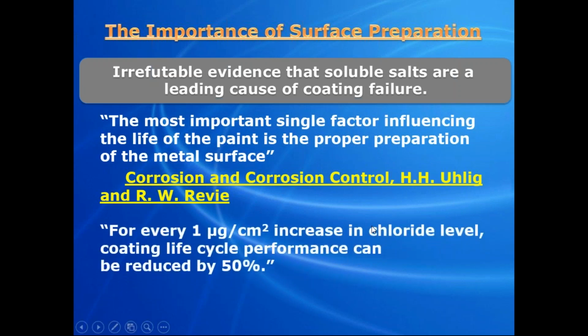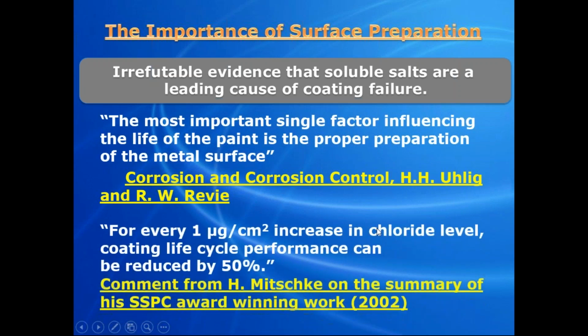Further to this, Howard Mitschke, then with Shell Global Solutions, conducted an extensive study on the impact of salts on coating performance. He won an award from SSPC in 2002 with his paper entitled Effects of Chloride Contamination on the Performance of Tank and Vessel Linings. And he summarized the results of his findings as noted. For every 1 microgram per centimeter squared increase in chloride levels, the coating life cycle performance can be reduced by 50%.